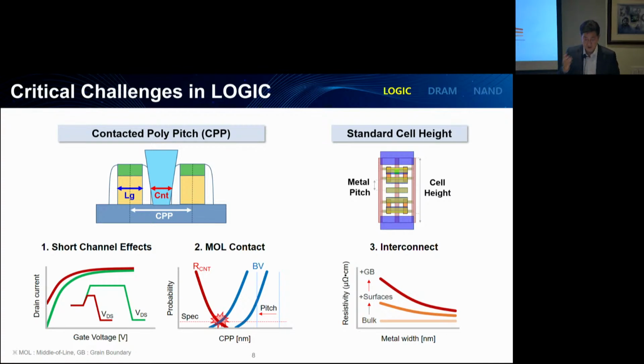So in order to scale down the CPP, we need to reduce the dimension of either the gate length or the contact size. However, decreasing the gate length induces large leakage current due to short channel effects, and decreasing the contact dimension increases contact resistance. On the other hand, in order to scale down the standard cell height, we need to reduce the metal pitch, and therefore the metal width. This inevitably increases metal resistivity due to non-trivial surface and grain boundary scattering. Therefore, critical challenges in logic transistors are reducing the short channel effects and improving the contact resistance and interconnect resistance. And in order to overcome these challenges, let us look into innovative approaches by focusing on the structures and metal materials.